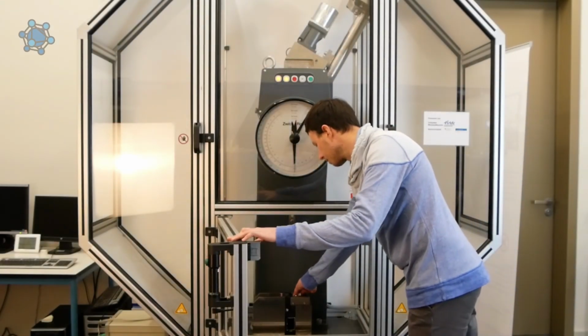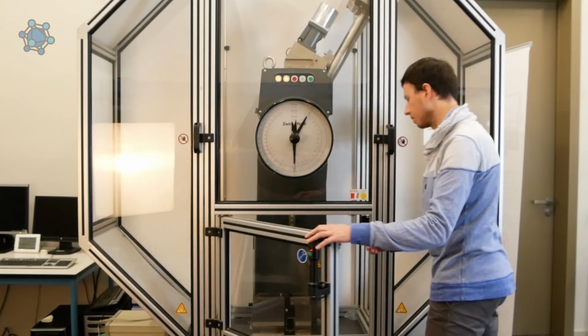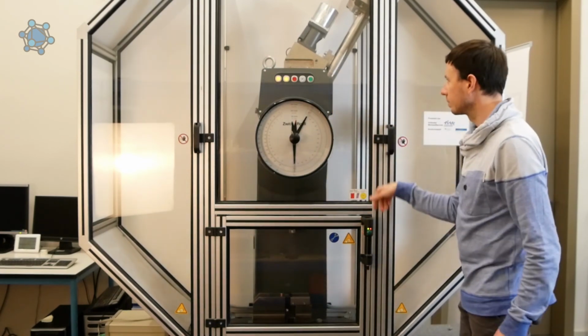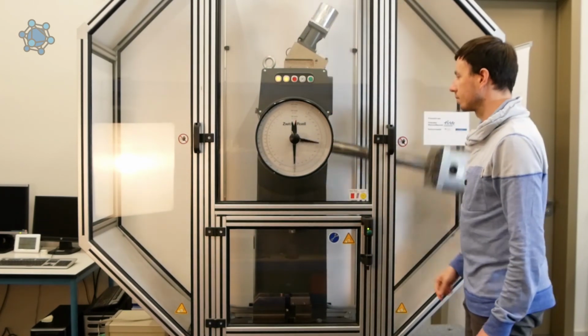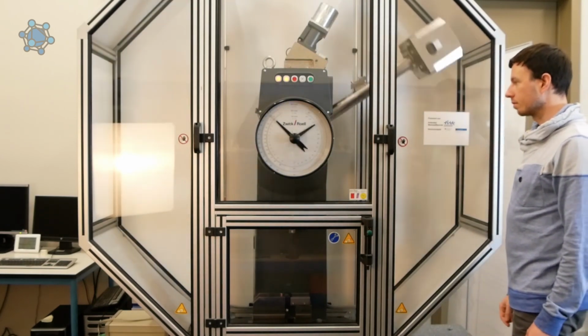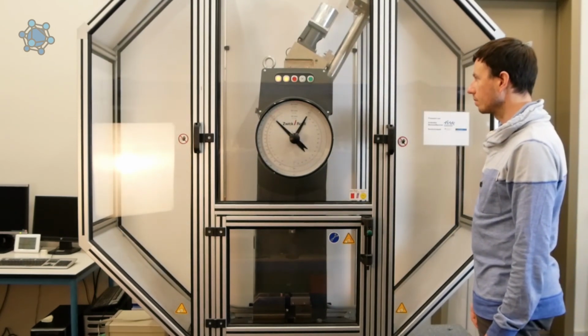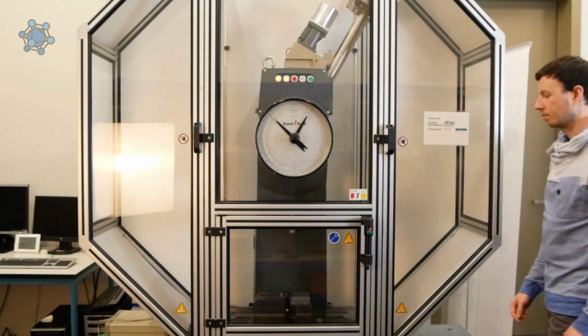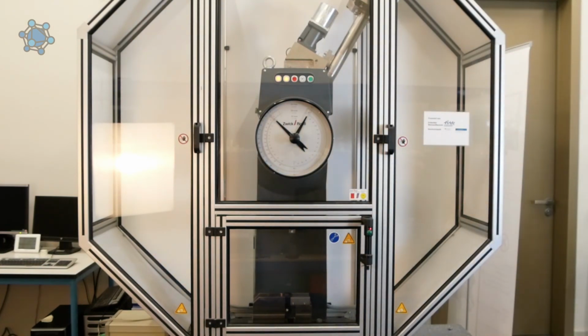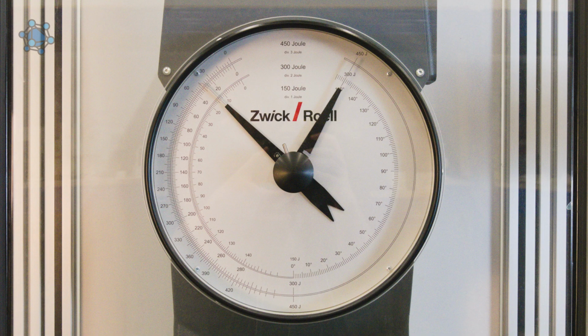The third test is performed with a specimen made of the material AlMgSi1, a type of aluminium. The specimen is again centered in the supports and the display is set to 0. The test is started, and on impact you can hear that the bang has a high pitch, similar to the first test. The specimen has a V-notch impact energy of 41, scoring between the C45 and the 1.4301.